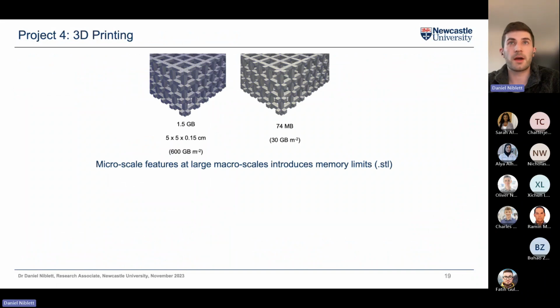And as you can see by these images here, sometimes when you're trying to print large macro scale materials with micro scale features, you can actually introduce memory limits onto your structure because, for example, a 5 by 5 centimeter piece of this material was about 600 gigabytes per meter squared of this material. So if you were printing larger sizes to go into commercial scale electrolyzers, fuel cells, which are meters in scale, then you'd have to address the memory limits of traditional surface files.